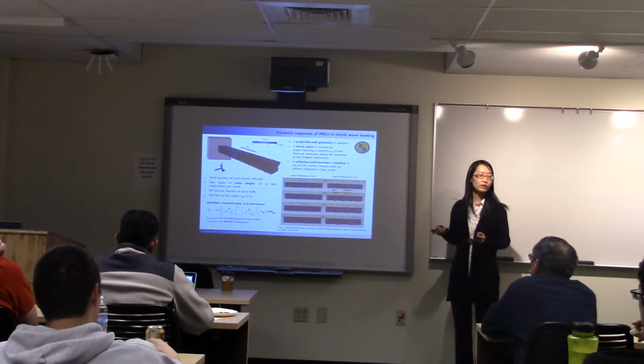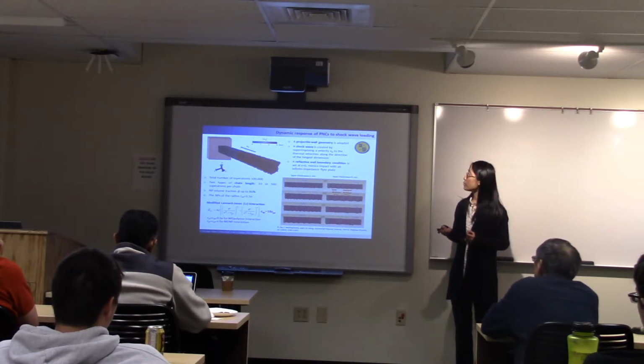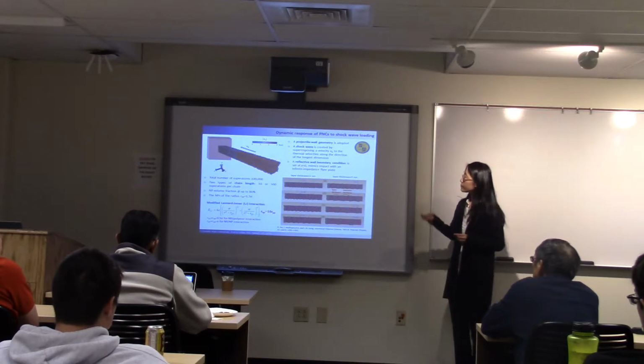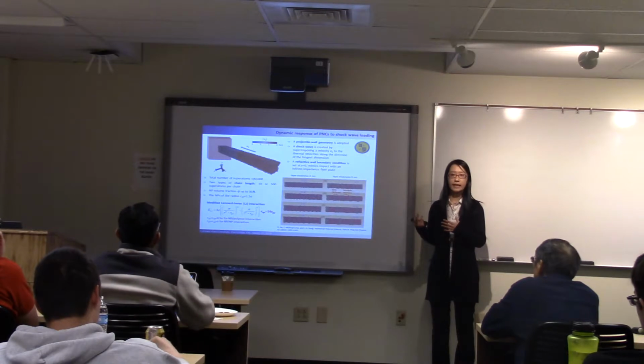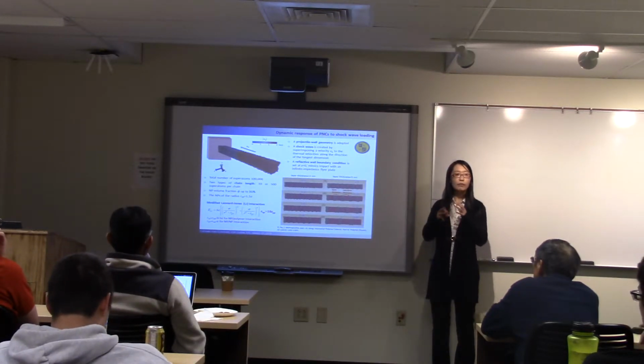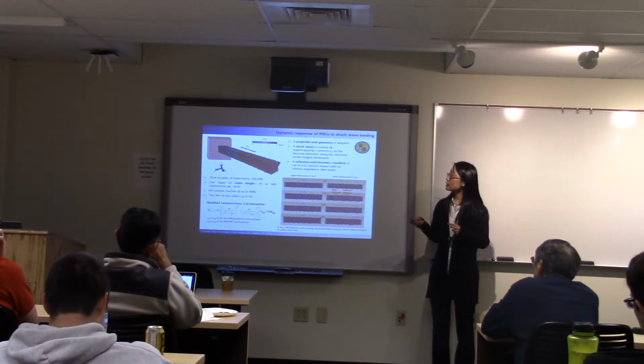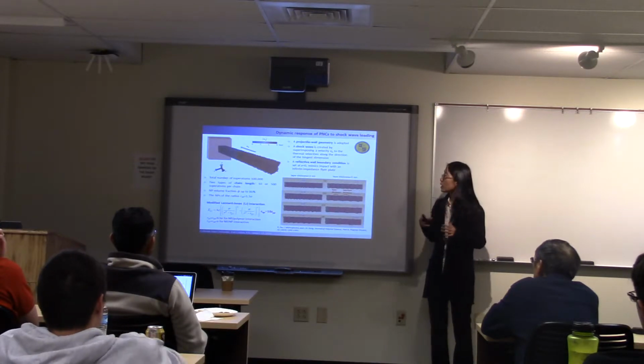We further did some study on the dynamic response to shockwave loading, and this project is of interest to our collaborator at the Naval Research Laboratory for polymer usage, like a polymer film for shock mitigation. So the general system is similar to the one we previously did, but we made a simple modification to the nanoparticle structure. We didn't put superatoms on the surface; rather we just used one sphere to represent the nanoparticles.